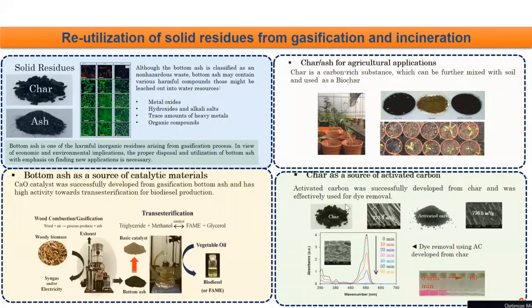This slide shows you our prior work regarding the use of biochar for different applications, such as for agriculture to grow water spinach, and as a source material to produce activated carbon, hence to do the treatment of wastewater to remove pollutants. The bottom ash from the gasification can be used as a source for catalyst. As shown here, we have successfully used this bottom ash towards the production of biodiesel.